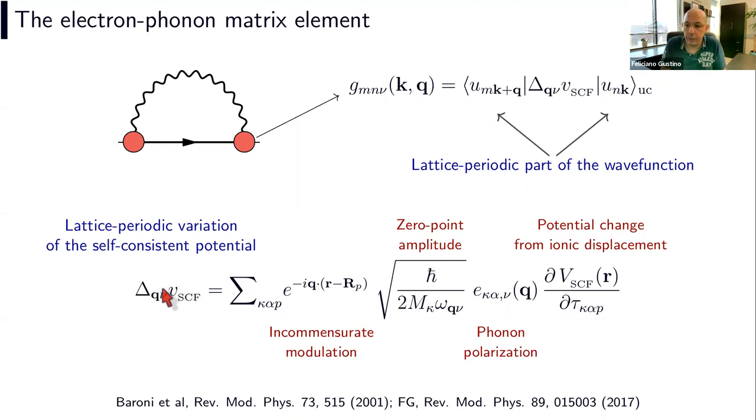The complexity of calculating this potential is that, while it can certainly be done with codes like Quantum Espresso or Abinit, essentially by density functional perturbation theory, the challenge is that each calculation for each wave vector is approximately as expensive as a DFT total energy calculation. One could say that should not be too complicated because I can just calculate maybe a dozen matrix elements and I'm done. The problem is that that's not the case, and one needs a lot of matrix elements to perform calculations.